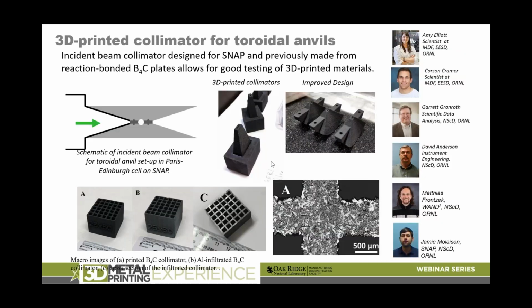And then just real quickly, some other things that we explore with binder jet are some of those non-weldable materials. So lots of carbides. This is boron carbide. And like I said, we have the world's most powerful neutron beam. One of the things that they struggle with is trying to more or less focus the beam or basically filter out stray particles, and they do that with these collimators. Boron carbide is one of the best collimating materials, but it's very brittle and hard to machine. So typically when they make parts, they're making really blocky, not fancy shapes like here in the center. But when we 3D print them, we can print the powder really well, and they don't really need a structure to it. They just need it to sit there. So we can do these very elaborate parts, and green form is acceptable to them.